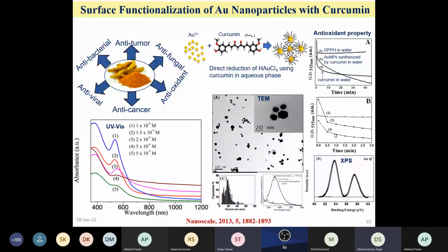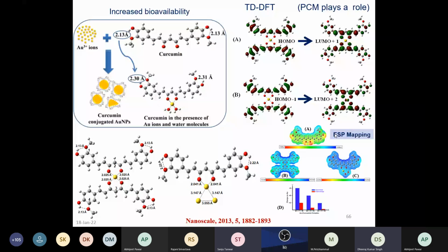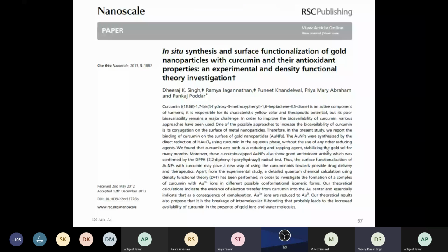In order to study surface functionalization and binding of curcumin with gold, I have also applied some quantum chemical calculation, that is theoretical calculation, and we have found that this is a curcumin molecule, haldi. There, this red one is oxygen, this is carbon, and this white is hydrogen. Now, in the presence of gold nanoparticle like this one, there is breakage of the intramolecular hydrogen bonding. Due to the breakage of intramolecular hydrogen bonding, the bioavailability of curcumin molecule is enhanced, and we have shown the binding of these 3 gold atoms to this curcumin molecule, and also HOMO-LUMO energy transfer from the curcumin, or metal ligand, to here. How the charge is transferred from the curcumin molecule to the quantum gold nanoparticle. And this is the color-wise charge transfer between the curcumin and gold nanoparticle. So overall, this paper was published in Nanoscale due to this application in antioxidant property of curcumin. And so this was the conclusion.